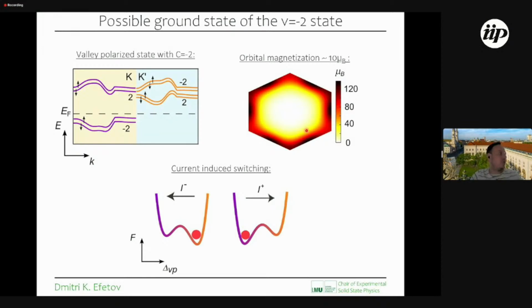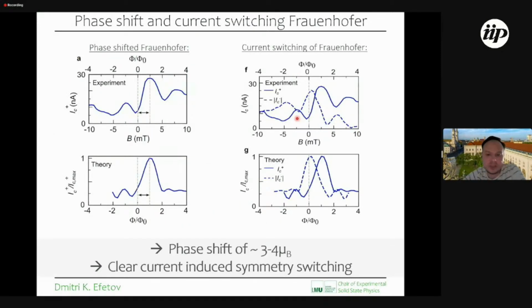And another thing which we found in the past, and other people who worked on these moiré systems, is that these magnetic states can often be switched by currents. Depending on the applied current direction, you can switch the magnetization of the state up or down. So the current couples to the magnetic moment, and it can reverse and switch it. And those are also things which you don't expect from a ferromagnet. And so we, of course, tried to see whether our experiments fulfill those signatures.